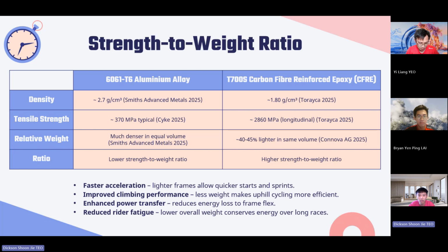CFRE, on the other hand, is much lighter at 1.8 gram per cubic centimeter and has a higher strength, with a tensile strength of 2,860 megapascal along the fiber direction. This difference means CFRE offers a far superior strength to weight ratio, which is critical for Olympic track cycling. A light frame accelerates faster, improves climbing efficiency, and reduces rider fatigue over long races. In fact, CFRE frames can be up to 40 to 45% lighter than aluminum alloy for the same volume, giving athletes a real competitive edge.